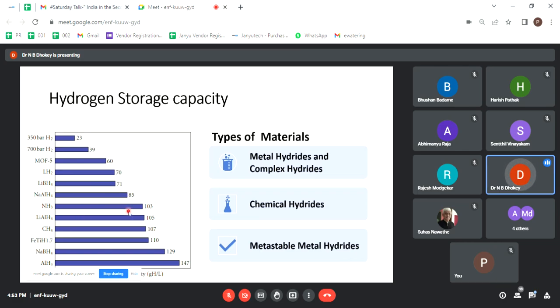Likewise, the storage capacity varies depending upon the compound and composition. Sodium borohydride is what is available commercially, a bit costly, and it has a very high capacity. Beyond that, aluminum hydride has more capacity to hold hydrogen. So this would come up as one of the hydrogen storage systems to run such onboard systems where you would like to run fuel cells. For fuel cells, you require hydrogen to make a vehicle green, and this hydrogen can be supplied by these metal hydrides, which are rechargeable.